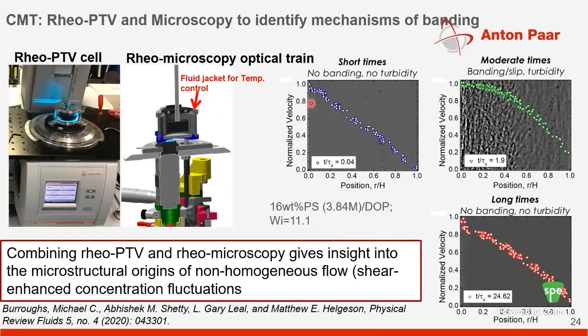If you look at the velocity profiles along with the overlaid microscopy images, you see that for these entangled polymers, this is actually a polystyrene and DOP type system. At short times, you basically have linear velocity fields, so there is no banding. And if you look at the microscopy image, there is no turbidity developing either.